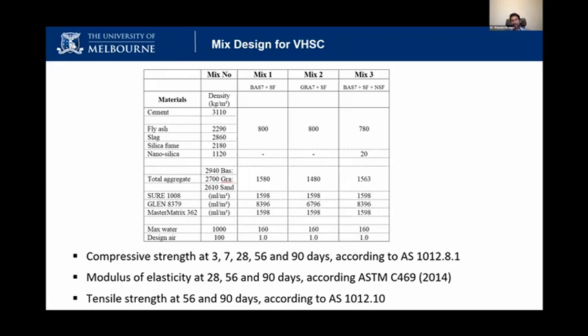Even Jan mentioned blended cement. If people have doubts about blended cement, I think this is a good example, because we achieved somewhere around 140 to 160 using this blend. The aggregate content is really high. That's the secret to reducing the cost. And we have used water reducing admixtures, viscosity modifiers and retarders, because it has to retain its slump for around 2 to 3 hours.